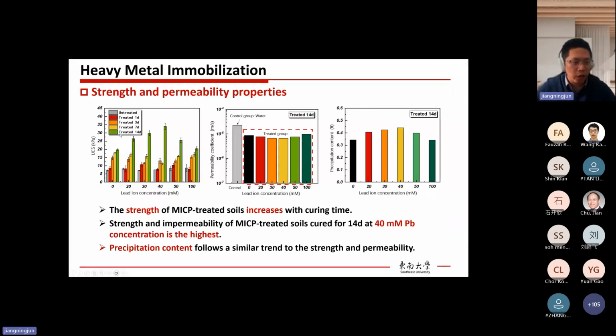Although the overall strength is not that high, the highest is only like 35 kPa. This is because we only do one-time treatment. Our target is not to achieve high strength, but immobilization is more important. So we don't do high strength, right? Then in this case, we find that after 14 days of treatment, and when the lead concentration is 40 millimole, we have the highest strength.